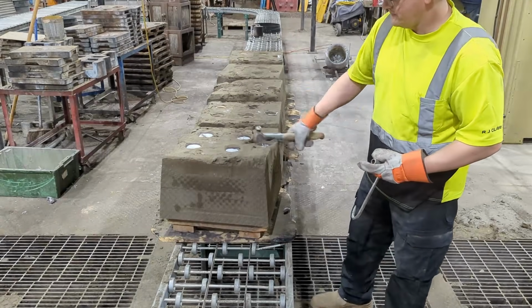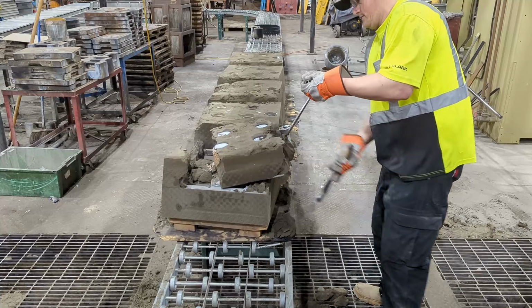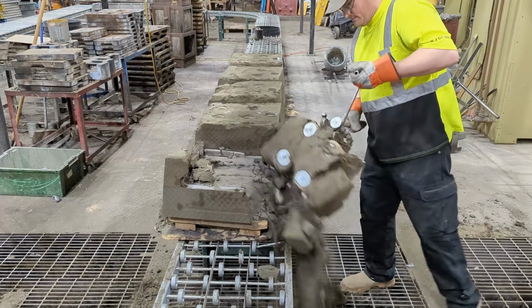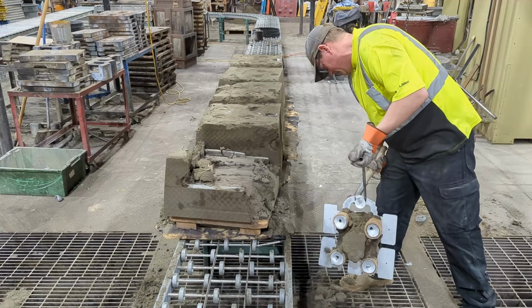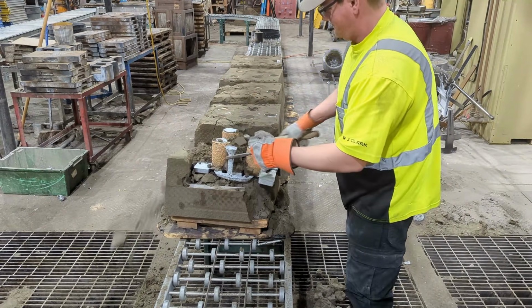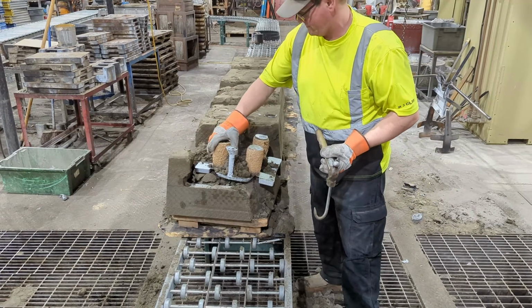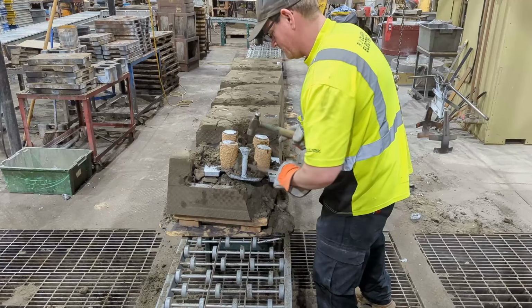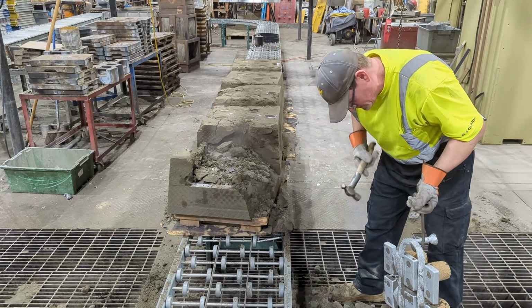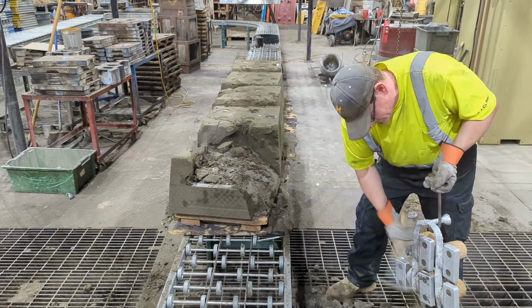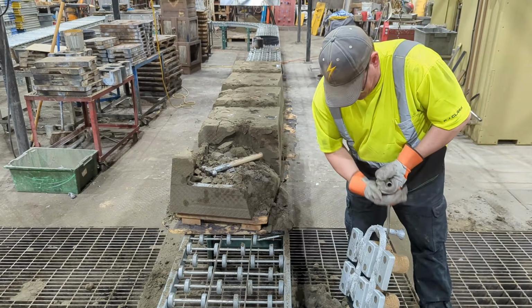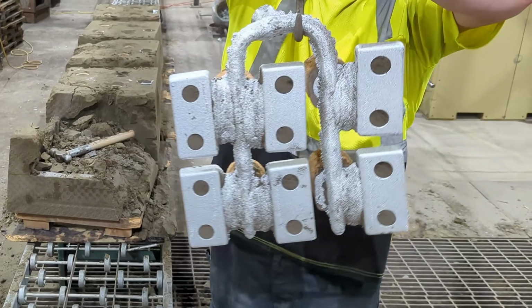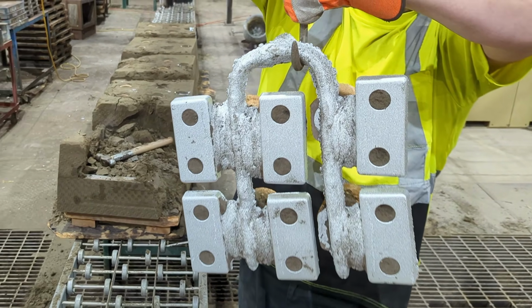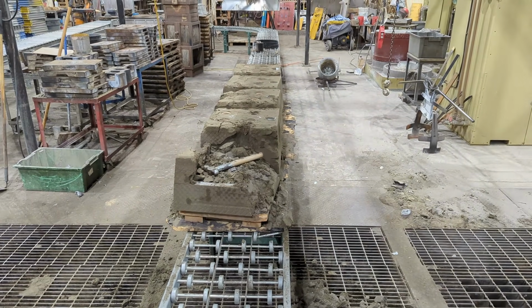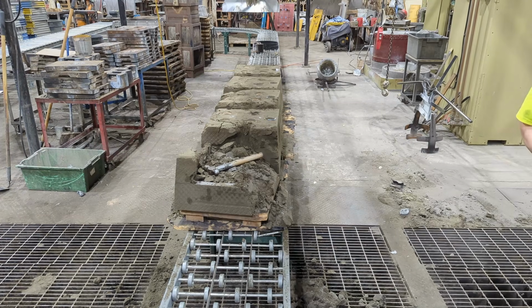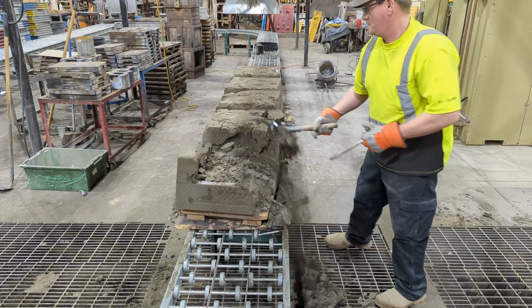After about 15 minutes, the zinc has solidified. Here, our team member Mitch breaks open the mold and lifts the casting out of the sand. He knocks away the loose sand and taps the runner bar to free any remaining sand from around the parts. Here you can see the finished product, 6 zinc anodes, freshly cast and still connected to the runner system. This process repeats for each remaining mold.